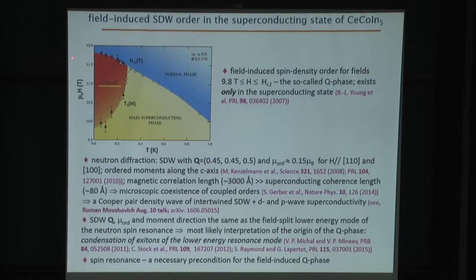So indeed, magnetic order is found in cerium cobalt indium-5 in a field of around 11 Tesla, and that magnetic order actually appears in a range of fields between roughly 9.8 and 11.6 Tesla. And this magnetic order exists in the so-called Q phase, which is only inside the superconducting state of cerium cobalt indium-5. So this upper boundary here is the upper critical field of cerium cobalt indium-5. So this field-induced magnetism exists only inside the superconducting state of cerium cobalt indium-5.